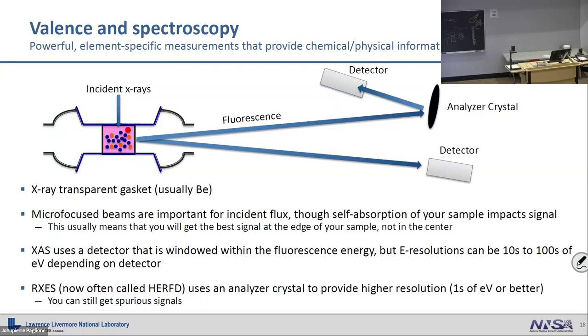want to look at. There's usually two types of spectroscopies that you end up with here. One is where you just basically have a detector out here and you go to an edge. So let's say you want to look at lanthanum. You go to the lanthanum X-ray edge, and you sweep your incident energy above and below that edge. When you go above the edge, it's going to start fluorescing. When you're below the edge, it's not. So you can tell where the edge is just by whether you get counts on the detector or not. So that would just be called partial fluorescence yield.